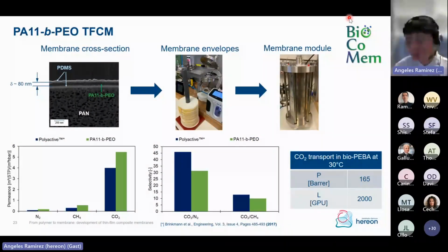Now, here we have some preliminary results that we obtained within the Biocomem project. As Anna was mentioning, we worked with one of the prototype PEBAs. We were able to prepare a thin film composite membrane here on this PDMS and PAN support. We upscaled the membrane, we prepared membrane envelopes, and we fabricated some membrane modules for lab and for piloting applications, which will be tested by our partners.